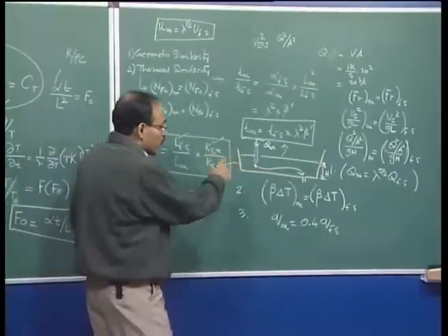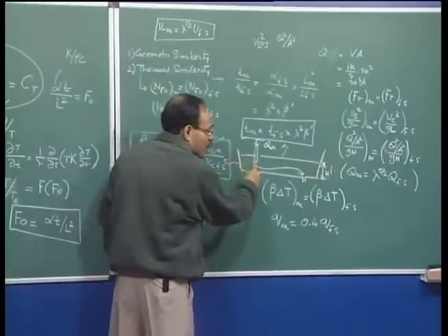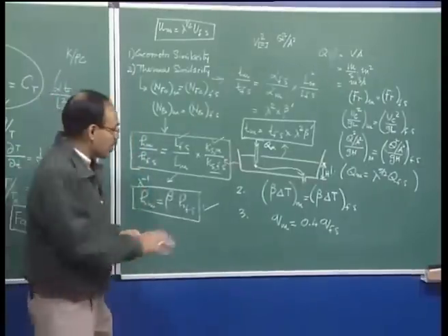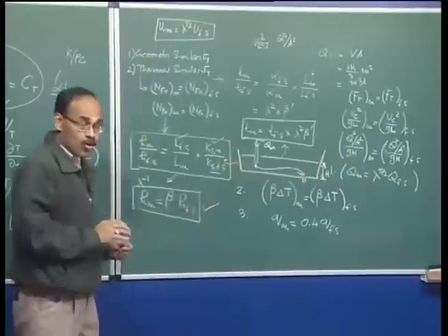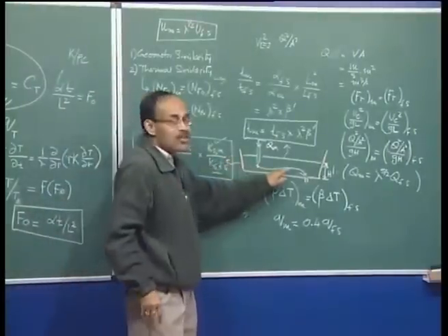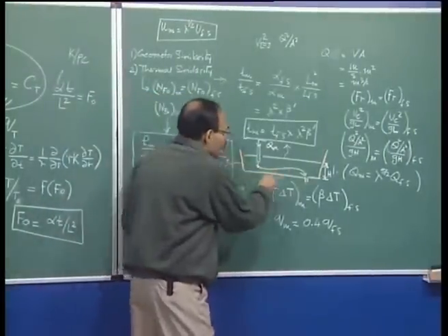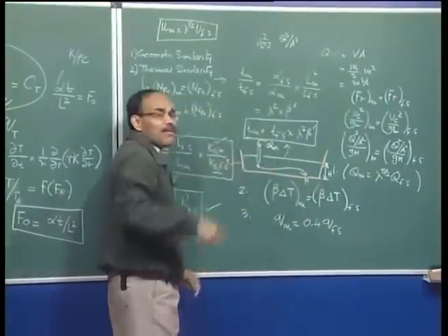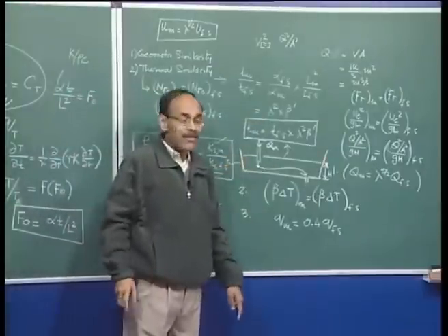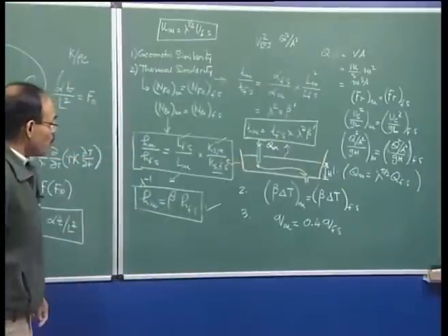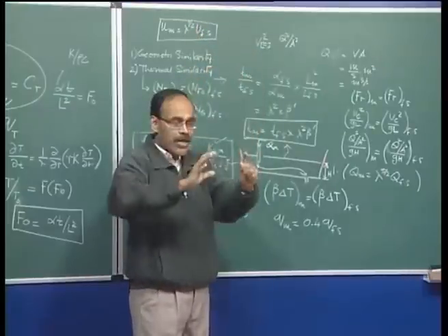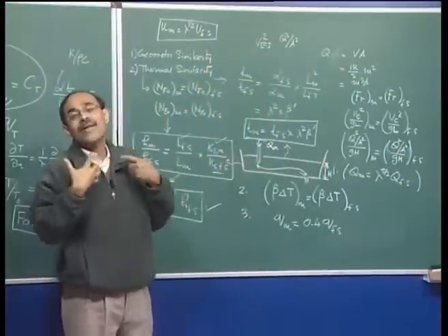And therefore, the metal comes here at 1600 degrees centigrade, but it does not go out through the strand at 1600 degrees centigrade. It goes out at a relatively lower temperature. There is a temperature gradient in the system. That is why we want to study that differential temperature or non-isothermal behavior. So, we are also going to use a vessel in which we put water at 95 degrees centigrade, but then there has to be some kind of heat loss also in order to replicate the exact behavior of steel flow in the tun dish system. And therefore, we consider the governing equations of fluid flow to get to the dynamic similarity criteria.